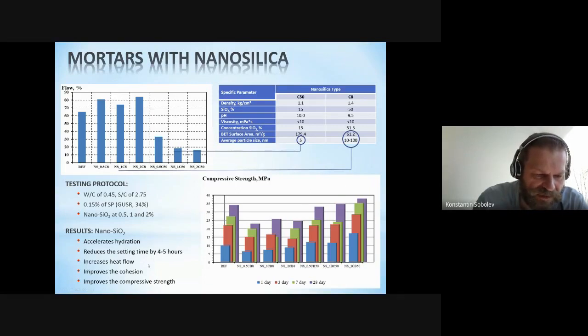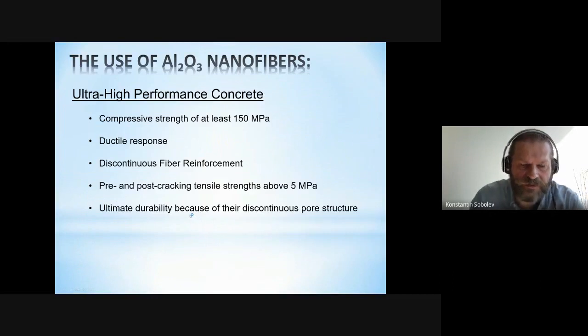So obviously nanosilica is a perfect viscosity modifying product, which improves the cohesion of the mix. It accelerates the hydration, reduces setting time, increases heat flow because it is again an accelerator, and improves the compressive strength. So this is the product which, I would say, is relatively cheap compared to other nanomaterials, which can really find its application in concrete.